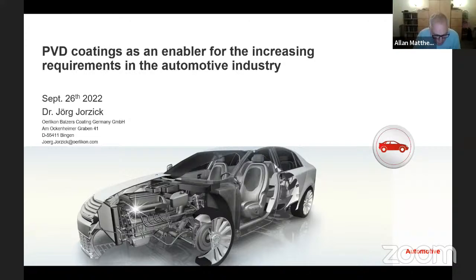Thank you. Balzers were one of the first to incorporate electron beam evaporation, weren't they? And I think they went more to arc and to sputter. Do you still see a future for electron beam at all? Yes. The electron beam evaporation is very good if you look for very smooth coatings. So there are certain fields, especially in semiconductor applications, where this is really one of the major requirements. And here, this technology, I think, will continue.